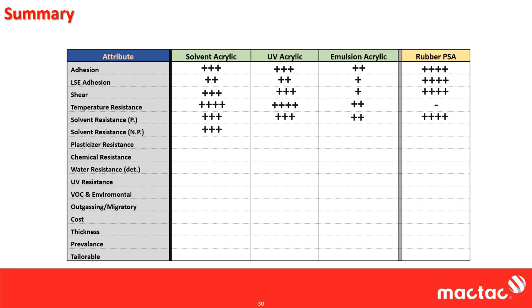Now, when you get to non-polar solvents, again, same for the solvent acrylic, UV acrylic, emulsion acrylics, you can get a little bit more solvating there. And with the rubber adhesives, they're terrible. They're going to solvate right in. As soon as you put like a heptane, a hexane, or a toluene, rubber PSAs are just going to fall right apart. Plasticizer resistance, all the acrylics are going to get high marks there.